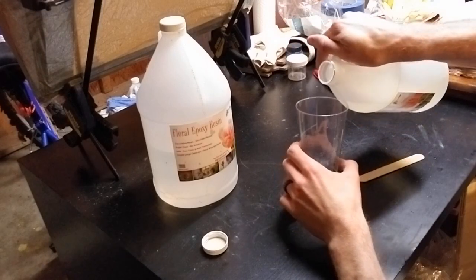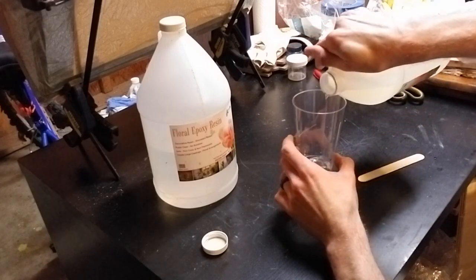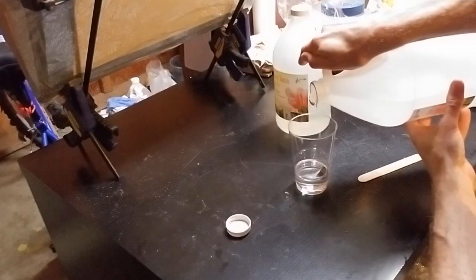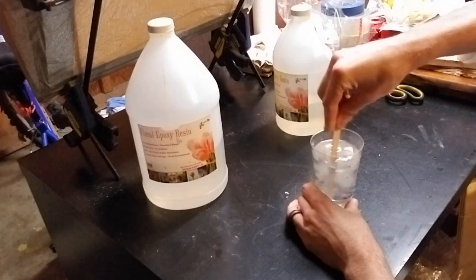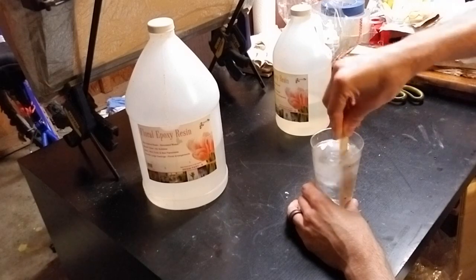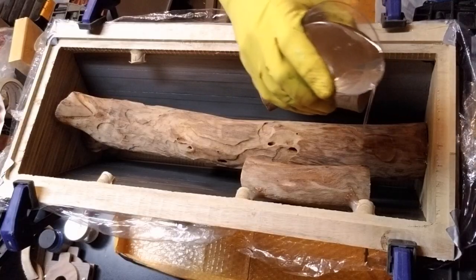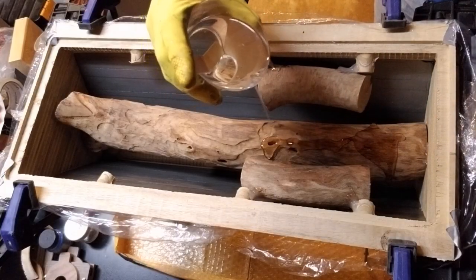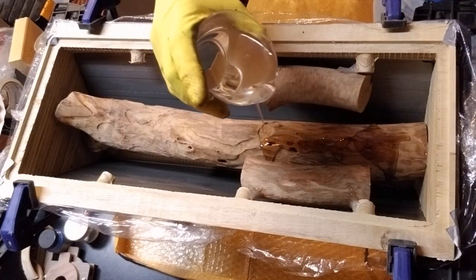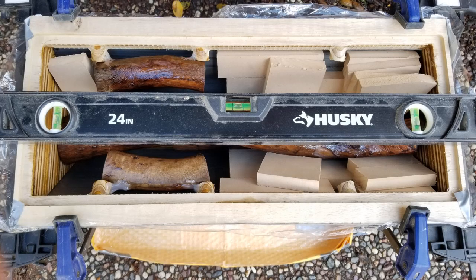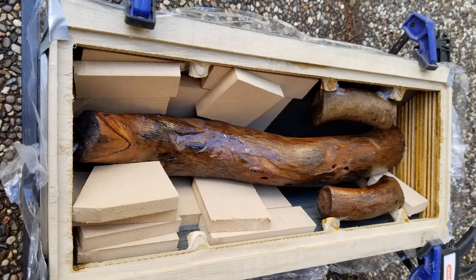With all these holes and cracks in the wood, I first used floral epoxy resin from the Epoxy Resin Store, as this type of epoxy is not as viscous as regular epoxy, so that it can easily fill all the voids. It also takes longer to solidify, so it has more time to release bubbles for a better bonding to the wood. I leveled the mold and put several pieces of scrap MDF in places that would not become part of the koi fish to save as much epoxy resin as possible.